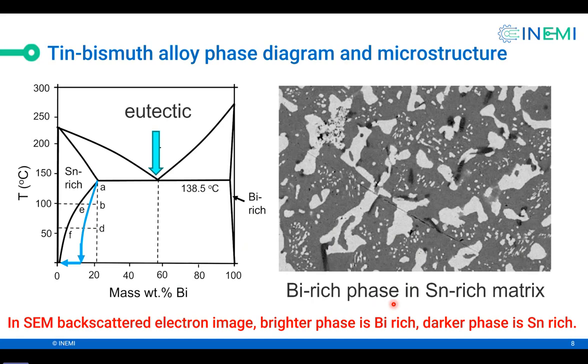So to get started, let me introduce tin bismuth solder. So this is eutectic solder in this case, shown by this blue arrow. So composition is 58% bismuth, and the rest is tin. So when we cool this alloy just below the eutectic, we get these large bismuth precipitation eutectic structure. The gray area is tin-rich, and the bright area is bismuth-rich.